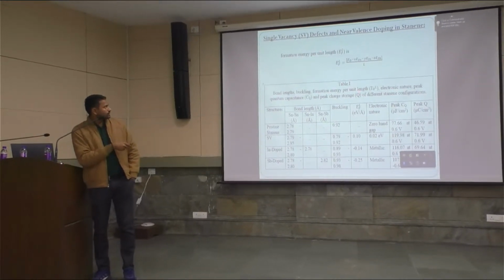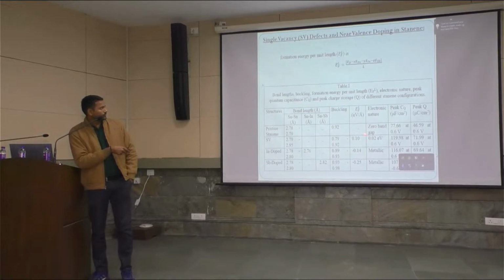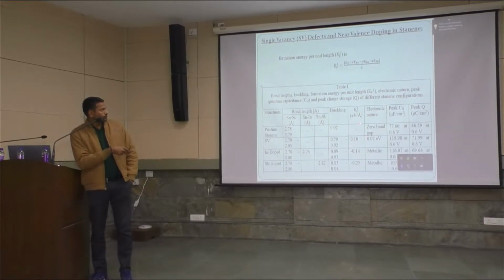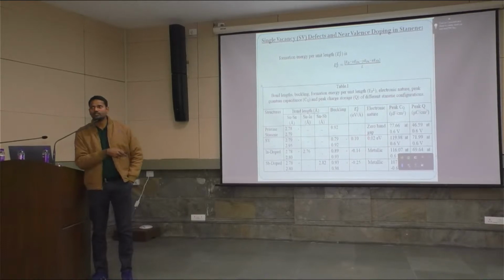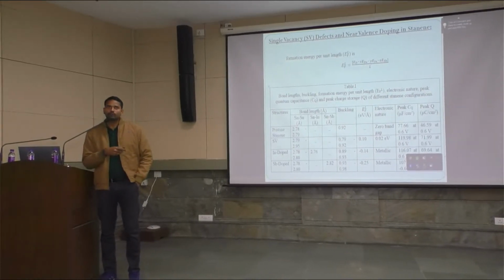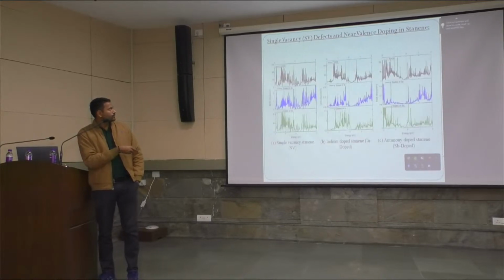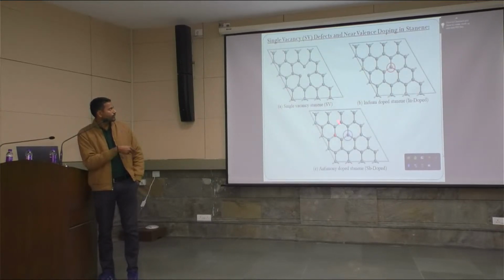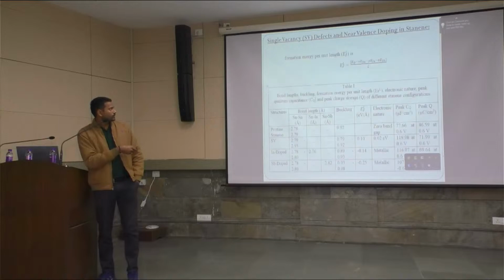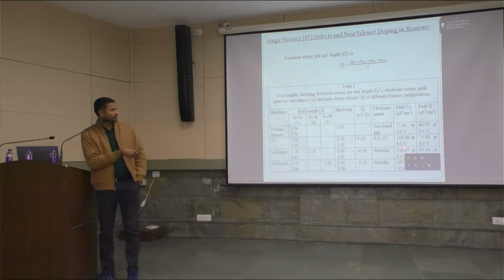when we looked at the formation energy, the stability is compromised, and the formation energy is positive here. It means the structure is unstable. So to increase the stability and to improve the quantum capacitance, we positioned the near-valency dopants, indium and antimony, at the SV site. Positioning the indium and antimony has improved the stability. We can see the negative value of the formation energy here. And the quantum capacitance also increased very much. It is 116 microfarads per centimeter square for indium, in comparison to pristine stanene's 77. Similarly, for antimony, it is 107.